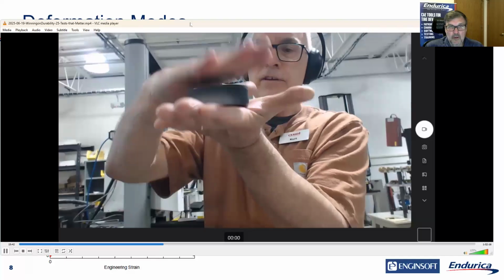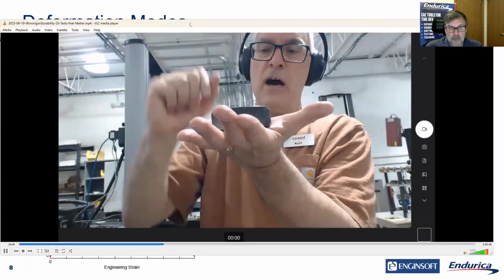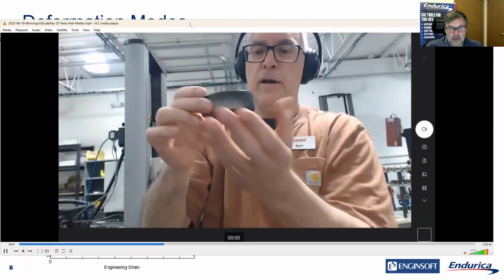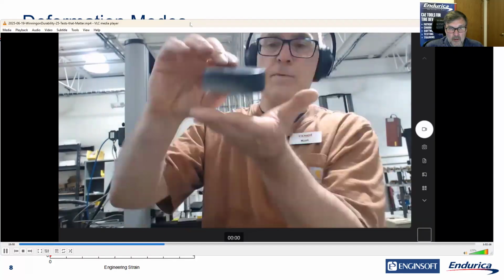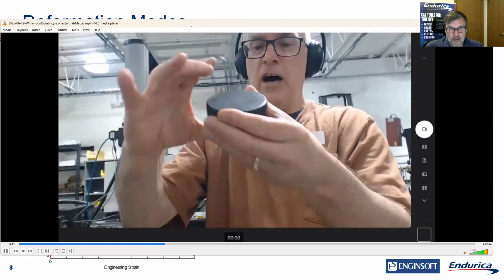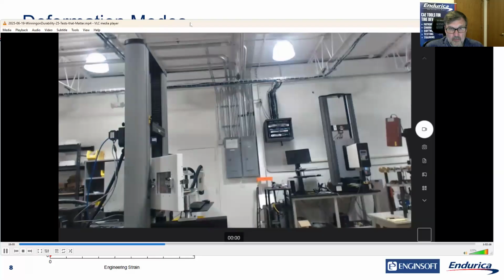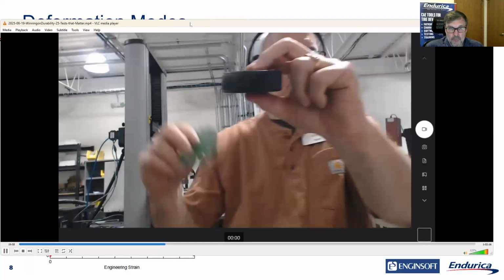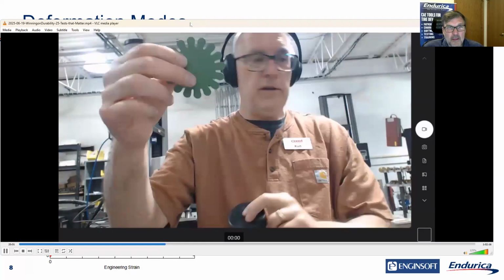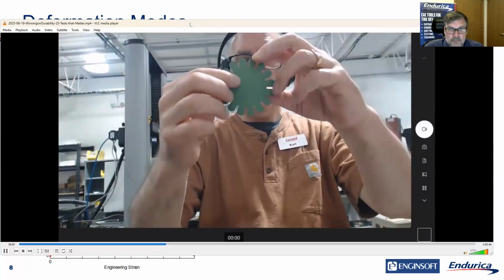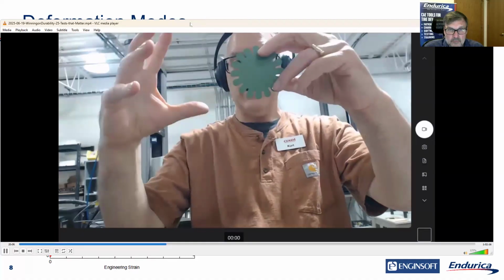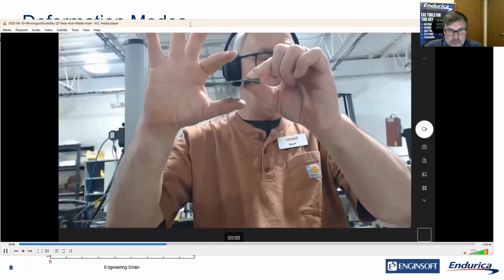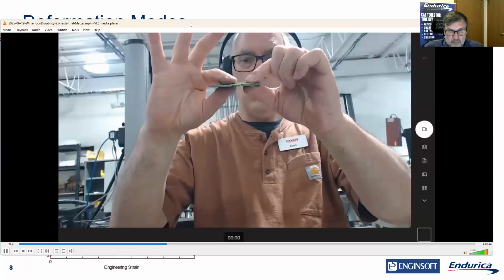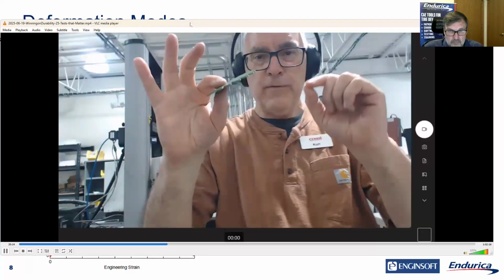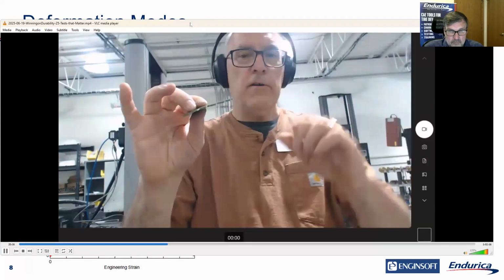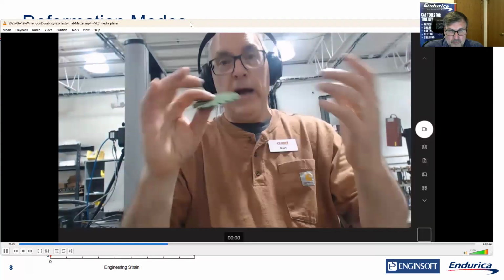So instead of compressing the hockey puck and getting the sides to squeeze out, and I suffer from a lot of friction, instead I'm just going to grab the perimeter of this thing, stretch it, and the top and the bottom will come together. So instead of using the disc, I'm going to use this shape. I'm going to pull on all the arms and stretch it. And when I do that, the top and the bottom of the specimen will come together. So if you're like a little piece of rubber living in the center there, you really don't know whether you're being compressed or whether you're being biaxially stretched.